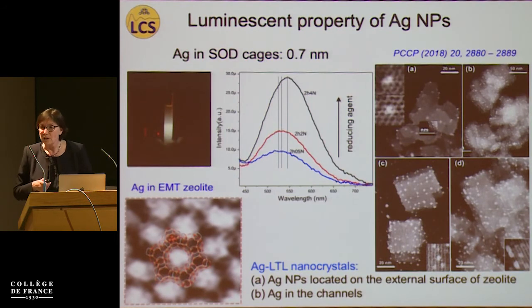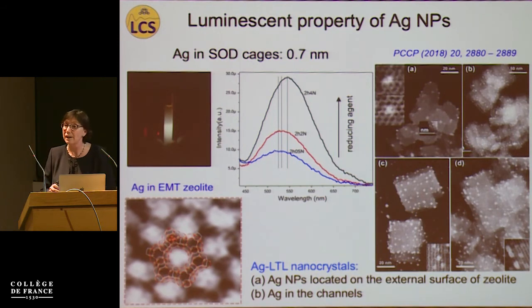Another advantage of using zeolite nanoparticles is the possibility to explore new properties of well-known metals. For example, silver stabilized in a microporous matrix, due to the size, would exhibit a plasmonic effect. But in our case, we have been able to put these silver nanoparticles in the sodalite cage of EMT-type zeolite, and as a result, we have seen that these particles are luminescent.